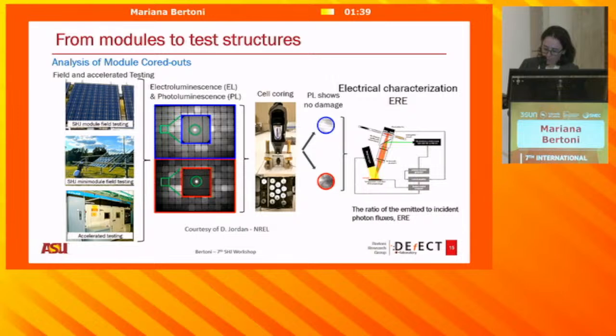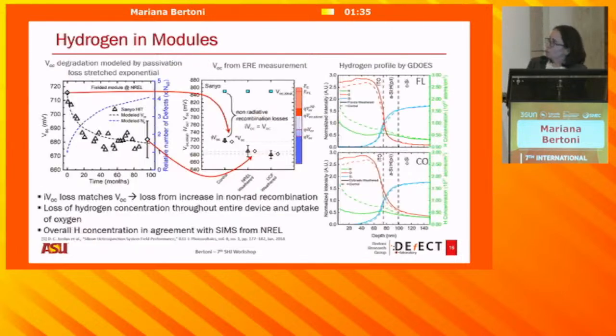So the next thing I want to briefly chat about is what happens when we go from modules to test structures. Same thing. Now what we did is we cored out a bunch of structures from the modules, and we measure basically the iVOC. One of the things that we see right away is that this is the initial value, and this is the module after a whole lot of months in the field. The first thing that we see is that our iVOC and our VOC are actually pretty similar, which suggests that the majority of our recombination is coming from non-radiative recombination.